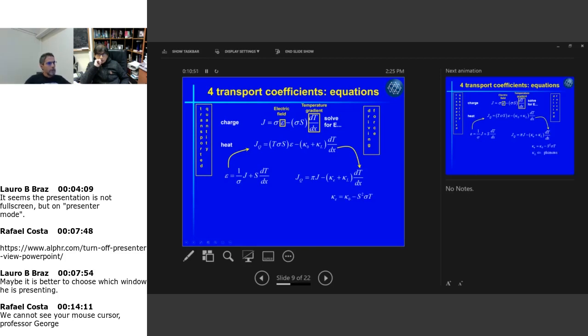of, in doing this transformation, you see that kappa E, which is the electronic thermal coefficient, is given by this expression, and kappa L gives you the amount of heat that is transported by the lattice. And this is important too. In reality, it's very important, as we're going to see.